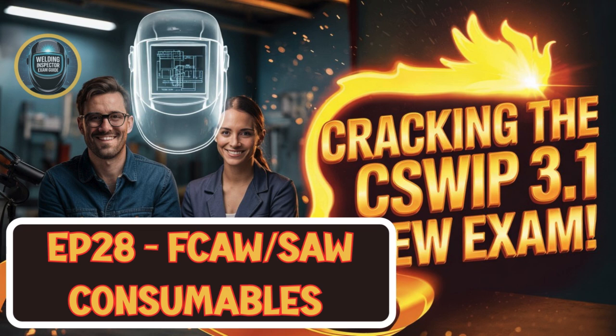You're absolutely right. The flux is far more than just a simple covering. It has multiple vital roles in SAW. First off, it shields the molten weld pool from the atmosphere. That prevents contamination from oxygen and nitrogen, which could seriously weaken the weld. It also actively cleans the weld pool, removing impurities, like a little chemical scrub. And crucially, it can actually modify the chemical composition of the weld metal itself.